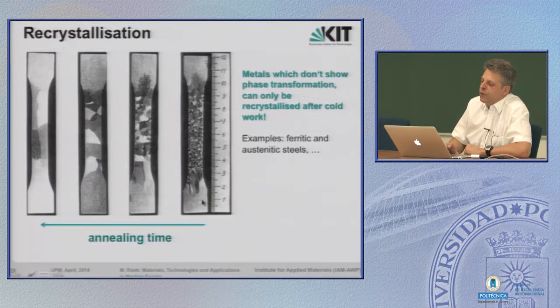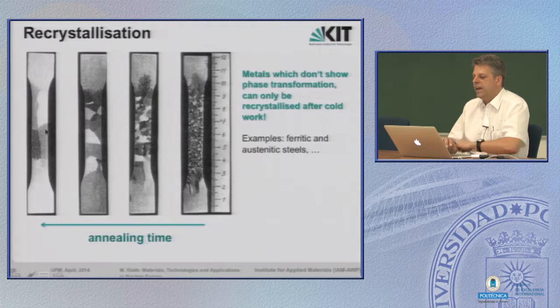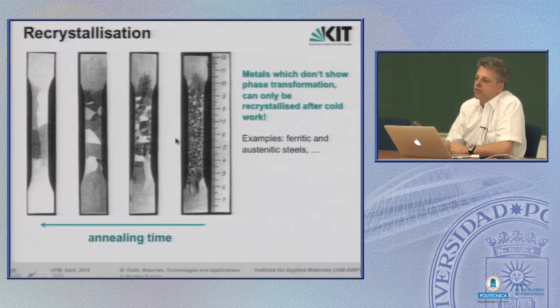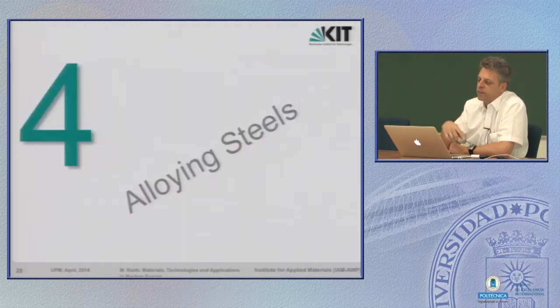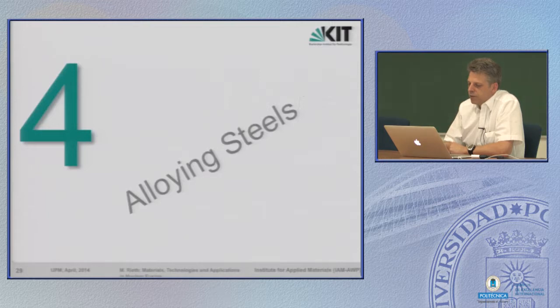And then if you heat them up, they start to recrystallize. This is shown here in a cold worked tensile specimen, and after some time, new fine grains nucleate, and with time they grow and grow and grow ever larger. And this is the only way how you can change the microstructure in austenitic steels or in ferritic steels. With ferritic steels, I mean, I will also come back to this later, steels which don't show this phase transformation. That's the basics of steels with respect to the microstructure and transformation.